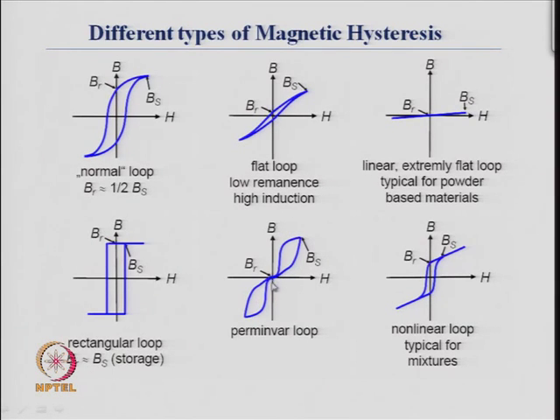Now, in this case there is 0 remanence. So, this is not a typical ferromagnetic material because the remanence is nearly 0. And this is a linear type flat loop, and this is typical for powder based material. There is hardly any remanence, it is nearly 0 remanence. And this is a non-linear loop, for mixtures. You can see that you have a ferromagnetic component shown by the hysteresis loop, but it never reaches saturation, it never becomes flat. You see, it is continuing to increase with increase in field strength. So, it is a kind of a non-linear loop, because the change in the magnetization is not directly proportional to the field.